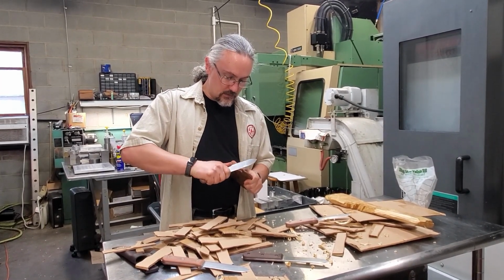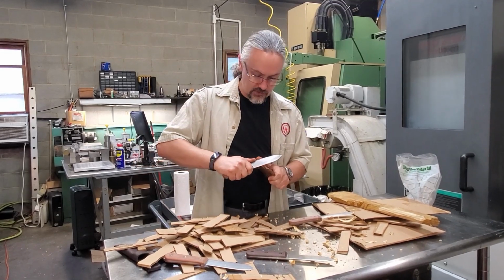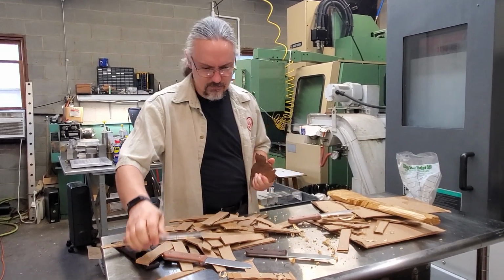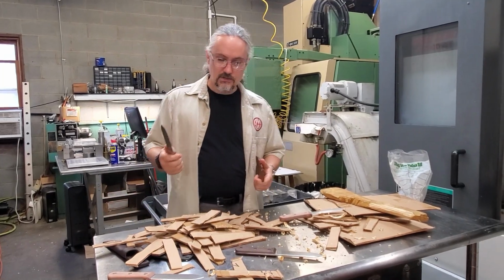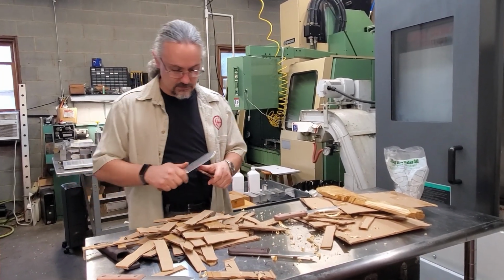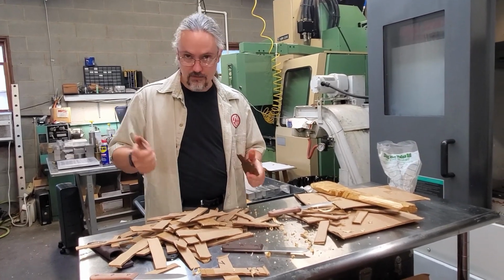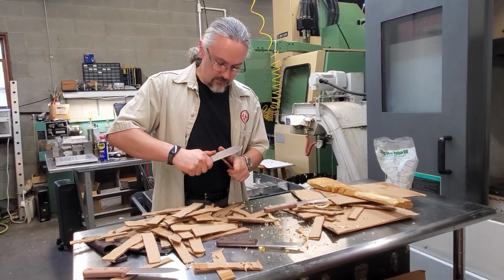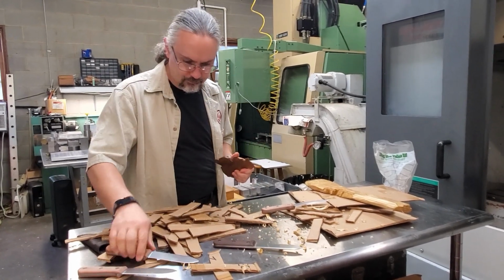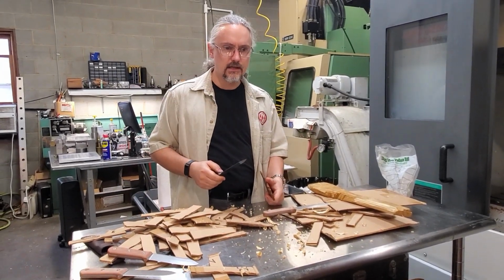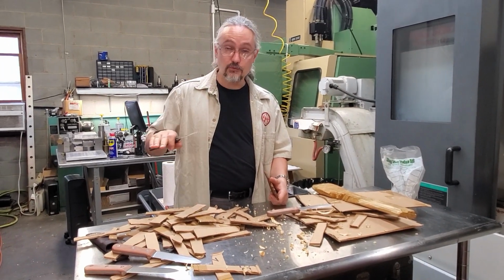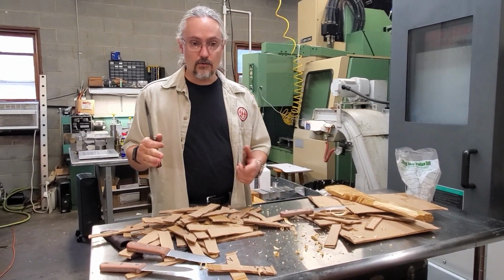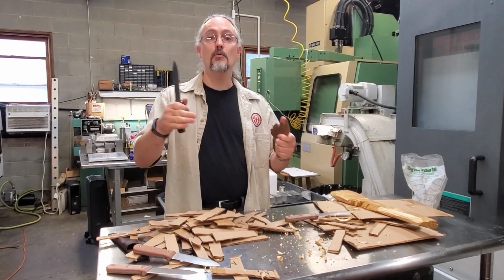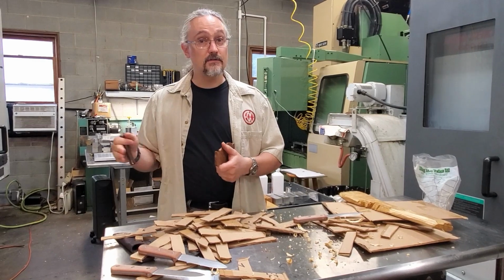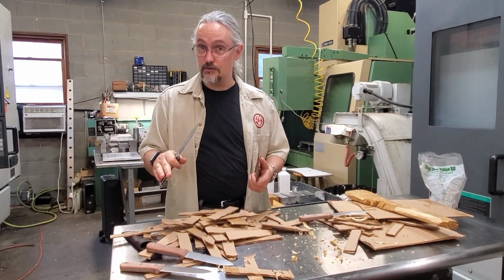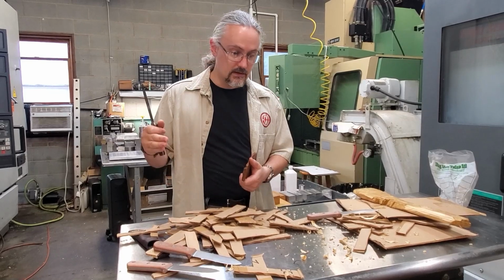Pre-quenching is something that I was doing with D2 to do grain refinement. It's kind of what it sounds like, but it's not what most people think you mean. Let's take D2 for example, because that's a steel we've talked about on the internet before. If you take D2 up to, let's say, 1750 degrees, which is below its normal austenitizing temperature, and you hold it there and then you quench it, and then you go up to, let's say, 1875 degrees, which is a little high, but maybe that's where I process it.